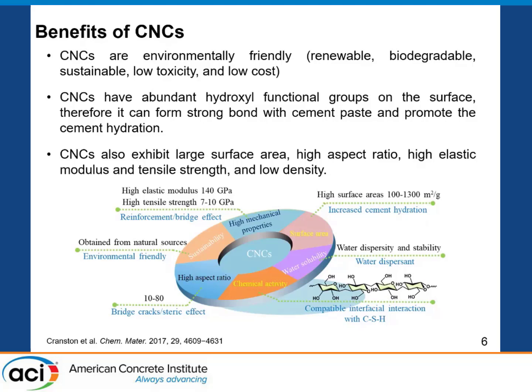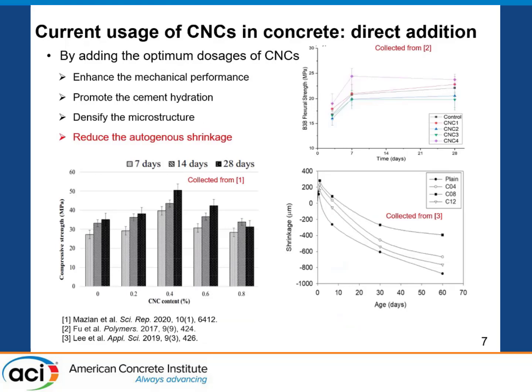Due to these unique features, it has been used for many applications, like treating some nanomaterials. But in concrete, people usually use it as an addition to cementitious systems, directly adding the dry powders or liquid suspensions into the concrete. As you can see in some of the literature, the mechanical properties with the optimum dosages are significantly improved, and the compressive and flexural strengths show a very significant improvement at the optimum dosages.